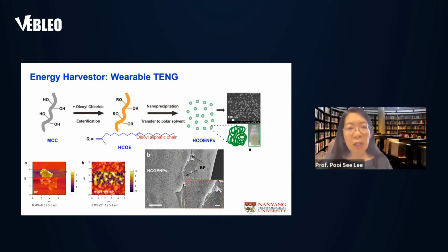By esterification and addition of oleoyl chloride, after the nanoprecipitation and transfer into a polar solvent, we convert the nanocellulose into a nanoparticle form that has the ester group on the surface. With that, these nanoparticles can be spray coated onto different substrates. At the same time, it endows it with hydrophobicity.